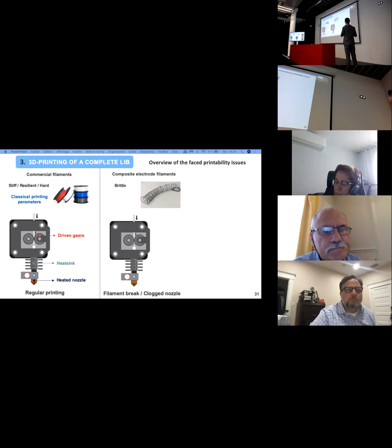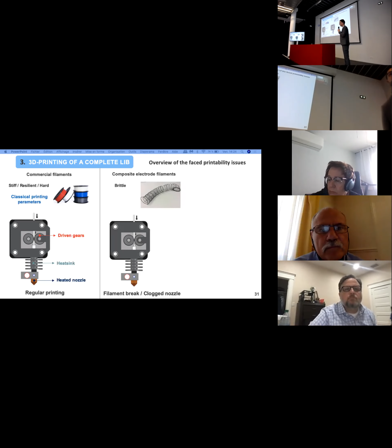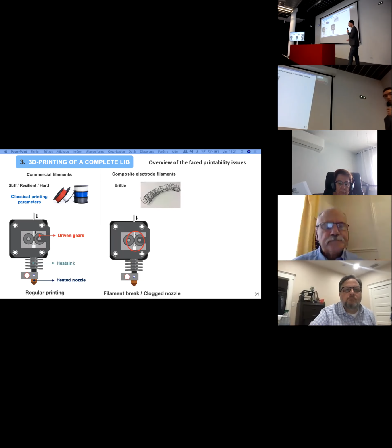If you take a look at the composite electrode filaments that we developed, they are clearly very brittle due to the very high amount of active material in charge. And so it will induce some filament breaks within the driven gears, and also some clogging within the nozzle. And this clogging and these filament breaks will then induce extrusion issues, meaning that right from the start or in the middle of the print, you will have no material coming out of your nozzle. And so this is quite a problematic issue.